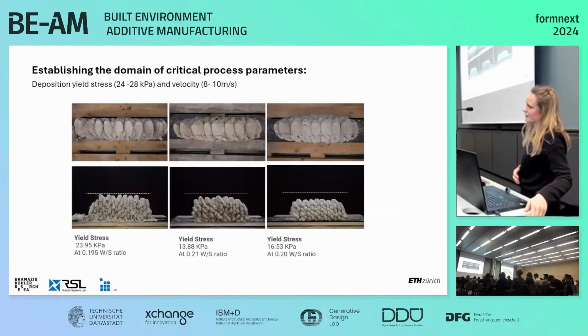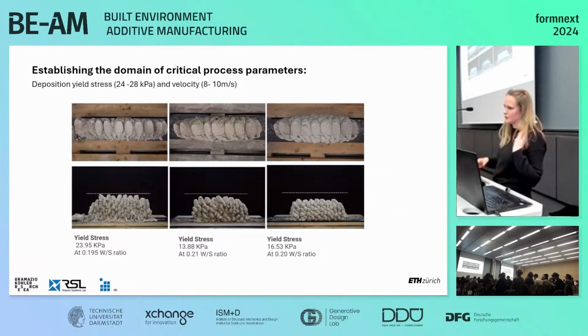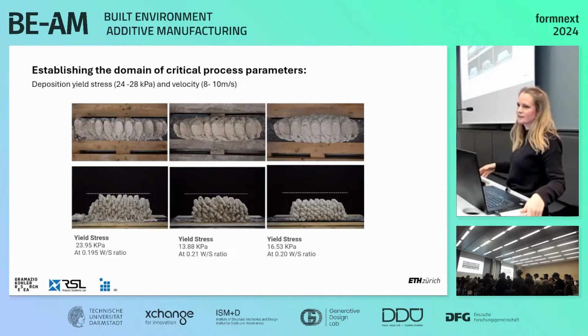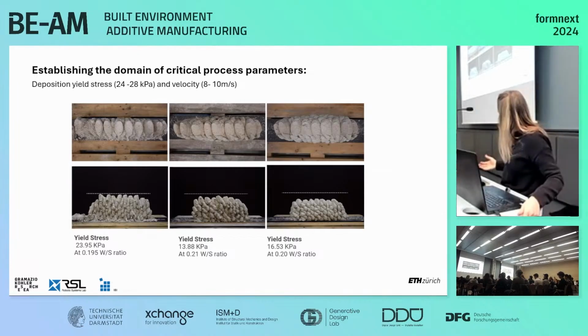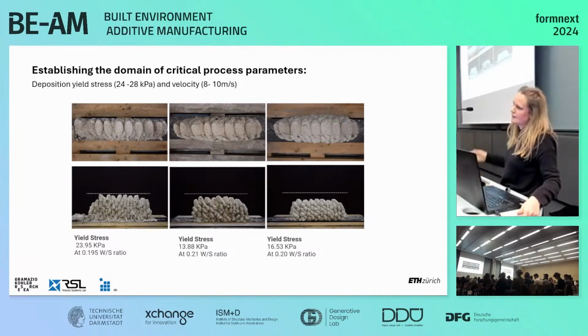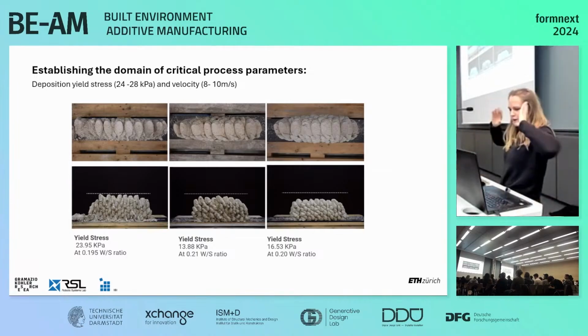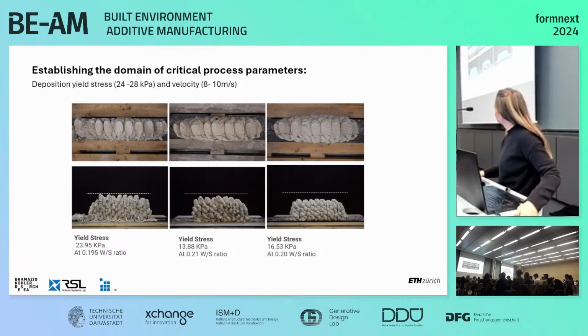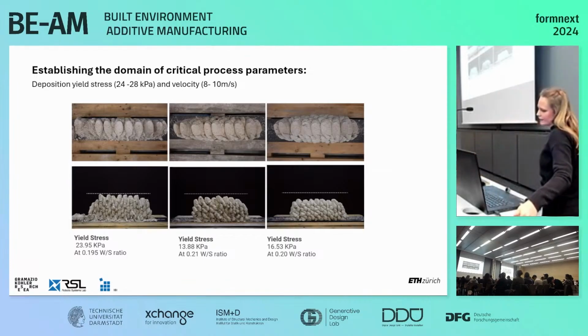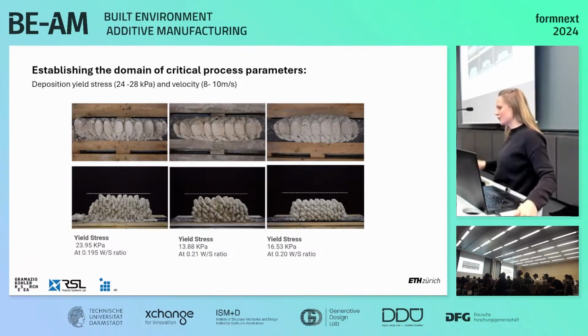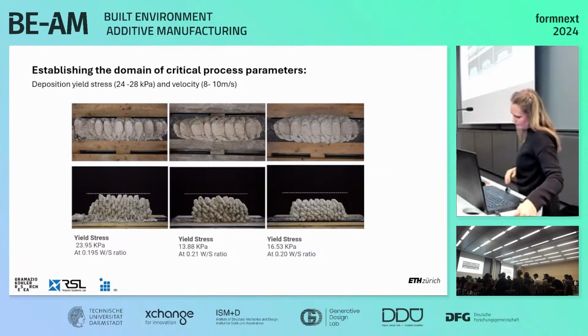Then there is the question of establishing the yield stress domain. So yield stress is the resistance of a material to deformation. And this is one of the most important material properties to control in terms of 3D printing, because you need to accelerate the yield stress in order to resist plastic failures from the weights above. And what we found in very early experiments is that we can increase the yield stress and shoot at a higher deposition velocity. And this basically means that if you can withstand the yield stress from shooting, you'll also be able to withstand the yield stress from many, many layers of vertical buildup. So we established a relationship that we're always aiming to start at greater than 24 kilopascals yield stress.